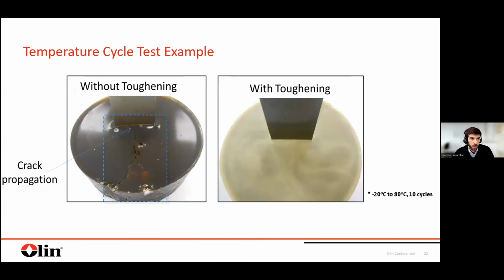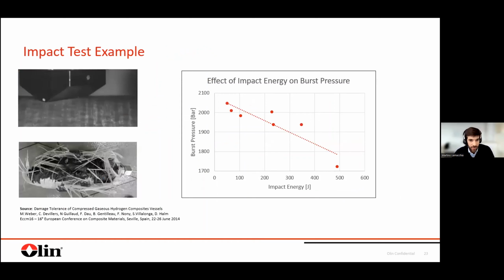The first example we want to show is the temperature cycle test. Here you see what happens to a clear cast of epoxy resin where a solid object has been put in to facilitate the generation of cracking. So what happens to this clear cast when it's cycled between -20 and 80 degrees for 10 times? You see the difference between a toughened epoxy resin and a non-toughened epoxy resin. And I think the pictures are self-explanatory, right? So you see how the selection of the proper matrix can make a difference, for example, in a temperature cycle test.